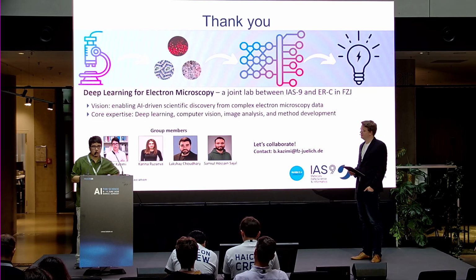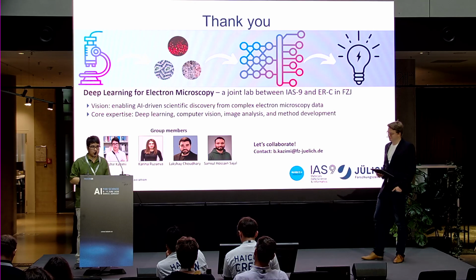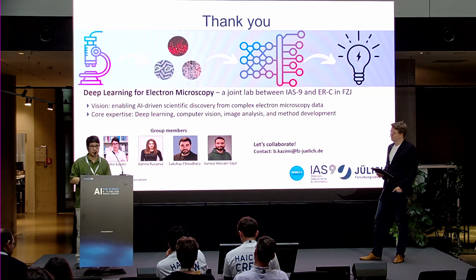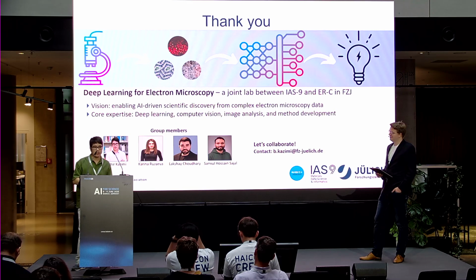Because, for example, in masked autoencoder, if you mask 75% of the image in order to pre-train your model, it doesn't matter much for the real space electron microscopy. But it matters a lot for the reciprocal space diffraction, because if your random seed somehow masks the central part of your diffraction pattern, you basically teach the model nothing. So that's why there's a discrepancy between the performances in different families of SSL models.